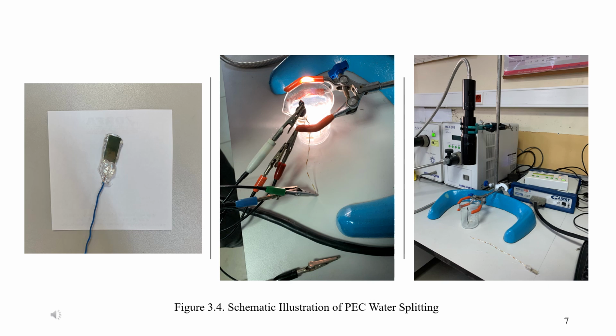The photoanodes produced for analysis to be carried out in light and dark environments were immersed in sodium sulfate and sodium sulfide sacrificial agent with a pH value of 13. The intensity of the light coming to the photoanodes was adjusted to 100 milliwatts per centimeter square, in other words, to 1 sun using a radiometer.